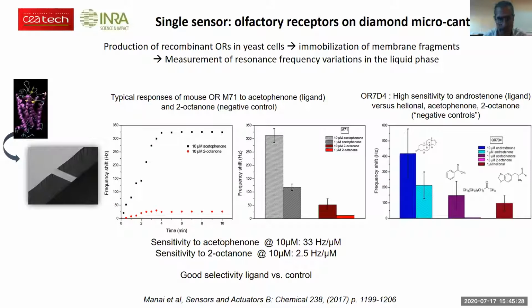A different approach, which is quite similar: we're using a different transducer here. We are using a diamond micro cantilever. So this is a diamond beam that was grown on silicon. We removed the silicon underneath. The size here is about a few hundred microns in length, a few microns in thickness. As we immobilize some olfactory receptors on the surface, and these receptors interact with ligands, they are actually increasing the mass load of this cantilever. And if we bring this sensor to resonance, then the resonance frequency of the device will be affected by mass loading on the surface by interaction with ligands.